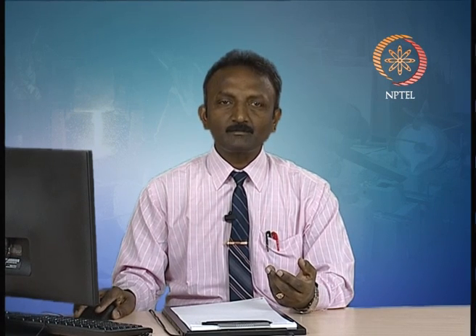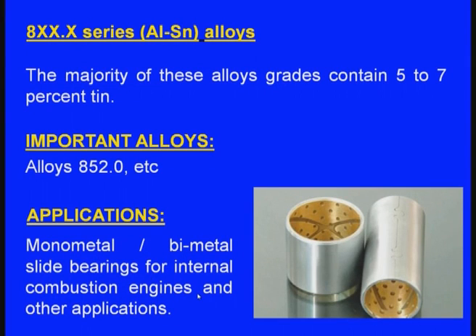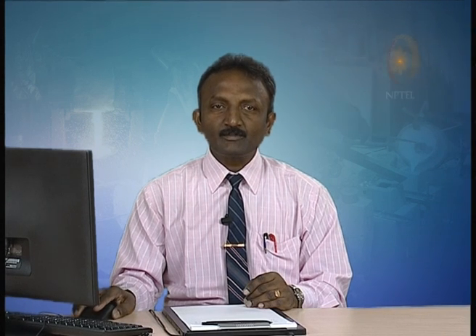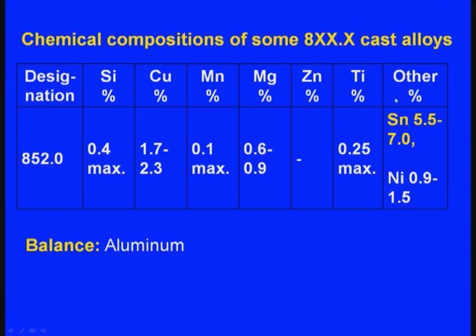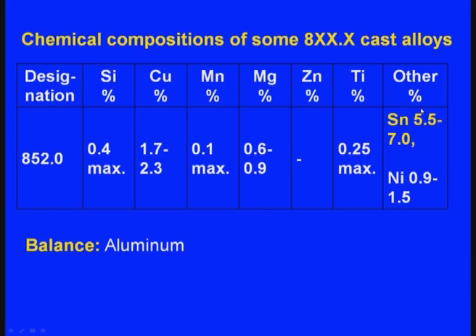In the 8xx series, tin is the major alloying element. The majority of these alloy grades contain 5 to 7 percent tin. An important alloy is 852.0. Applications include mono-metal and bi-metal slide bearings for internal combustion engines. Chemical composition of 852.0: silicon 0.4 maximum, copper 1.7 to 2.3 percent, manganese 0.1 percent maximum, magnesium 0.6 to 0.9 percent, tin 5.5 to 7 percent as the major alloying element, nickel 0.9 to 1.5 percent, and the balance is aluminum.